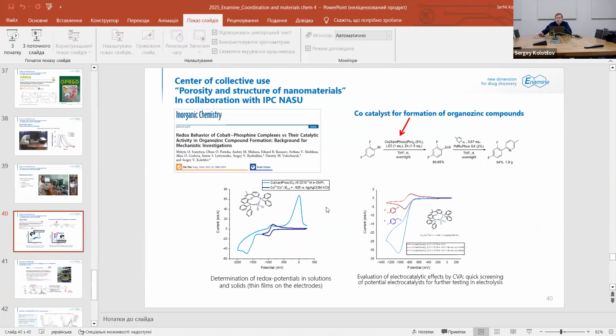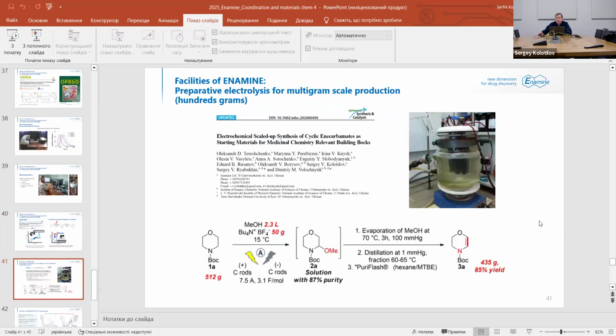And these complexes can act as a catalyst for formation of organozinc compounds, the equation you can see here. Just to evaluate electrocatalytic properties of these compounds, we measured cyclic voltammetry curves for one of the compounds. It's a cobalt complex with Xantphos. And upon addition of organic halides, in the right figure, the current of reduction grew very significantly, and it's a very good sign of electrocatalytic activity of this complex.